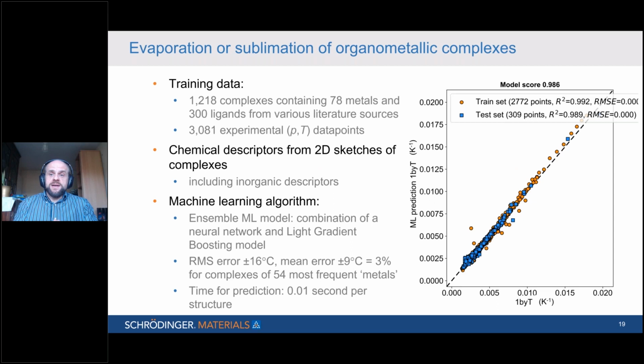This is the machine learning model that we've developed for evaporation temperature. We put together a training set of literature data for the pressure temperature relationships for the evaporation temperature or sublimation temperature of over 1,000 organometallic complexes that are typical for the area of vapor phase deposition. This spanned 78 metals and 300 ligands, and in fact there were 3,000 data points in all because we had multiple data points for many of the complexes.